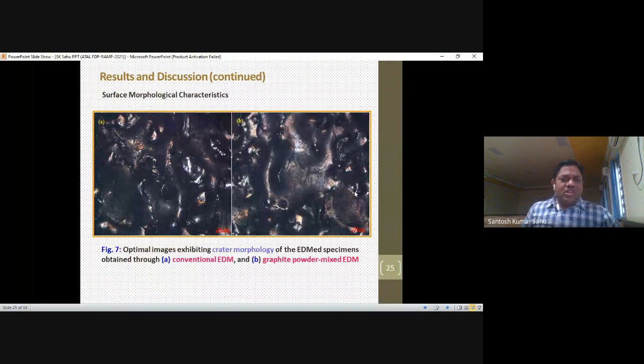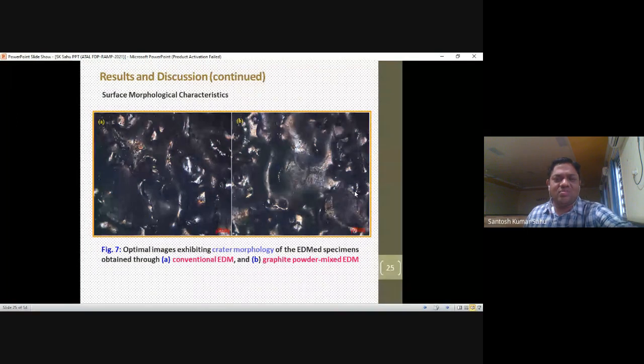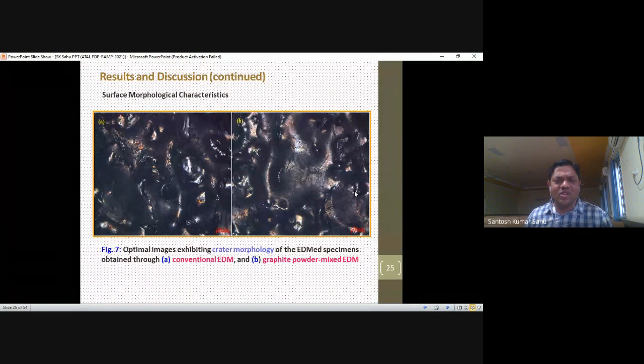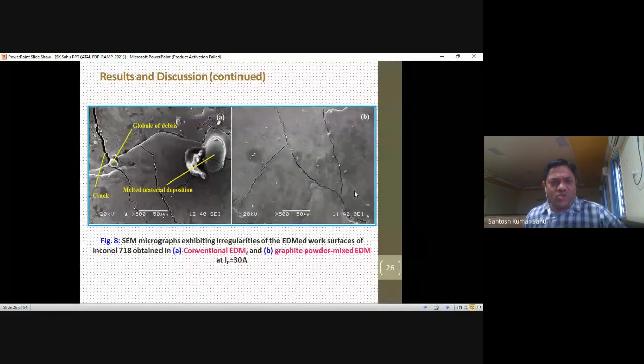Again, from figure number 7, we can see the optical image that exhibited the crater morphology of the EDM specimen obtained. Then you can see very clearly what the conventional EDM is. Another figure is the graphite powder mixed EDM, figure A and figure B. It is not very clear here, but to some extent we can see the surface morphology. The surface integrity we can see very clearly in the SEM figure. In that SEM micrograph we see the irregularities on the EDM work surface of our material with conventional EDM.